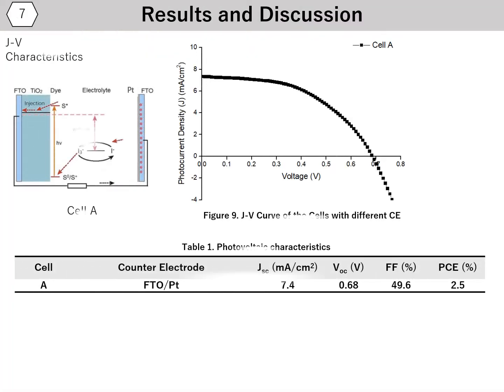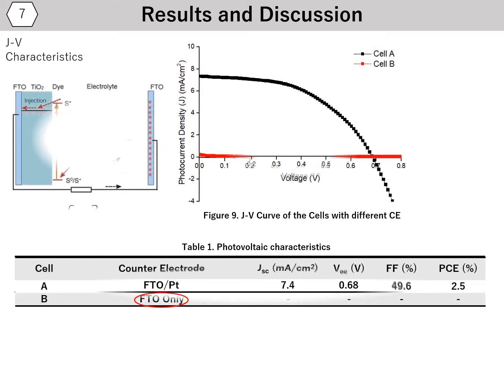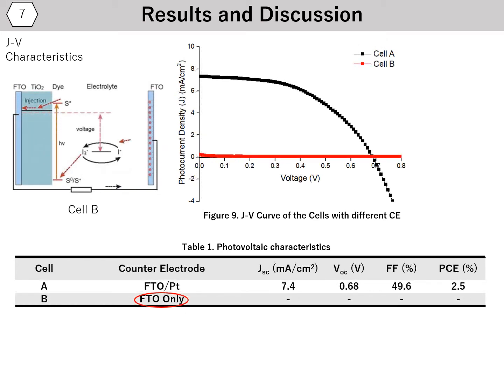The JV characteristics of the cell are shown in Figure 9. It was found that cell A that used platinum as counter electrode showed photocurrent density value of 7.4 mA per centimeter square, fill factor of 49.6%, and power conversion efficiency of 2.5%. However, when the counter electrode was replaced with FTO only, the diode characteristic was not observed.